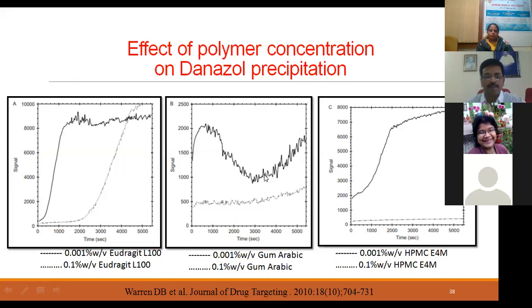Then coming to the second polymer, gum arabic. Gum arabic precipitation profile exhibited no effect on the precipitation process at low concentration. You see here, it is the same line. However, after 600 seconds, it is taken in the seconds, the danazole precipitate and the polymer flocculated such that the turbidity measurement was no longer valid. Actually, this study was carried out by nephelometry. The solutions were taken in the sample, and the turbidity that was obtained was recorded. So the time was taken on the x-axis, and the signal was recorded on the y-axis.